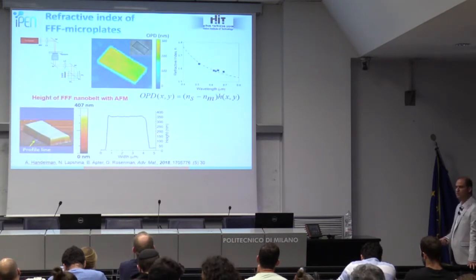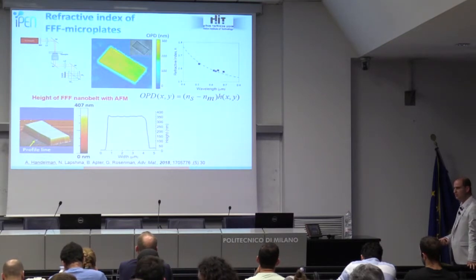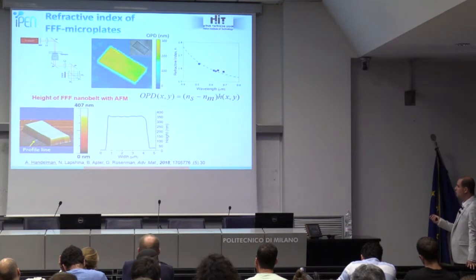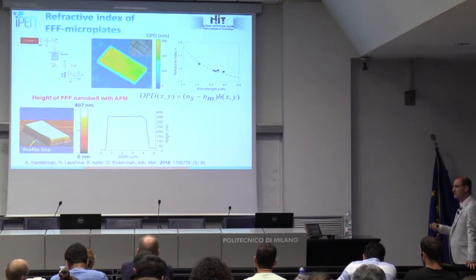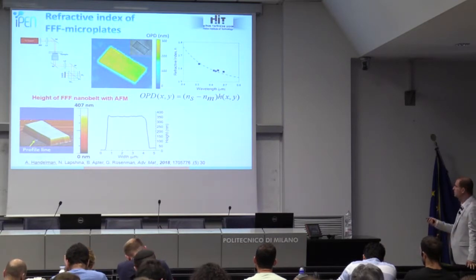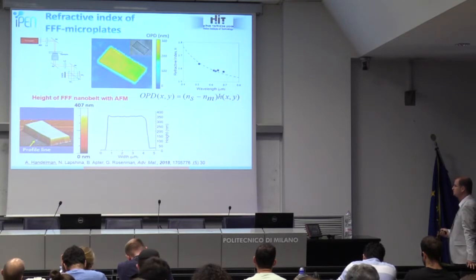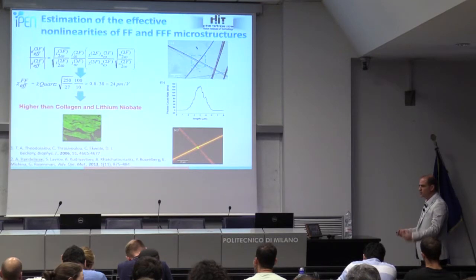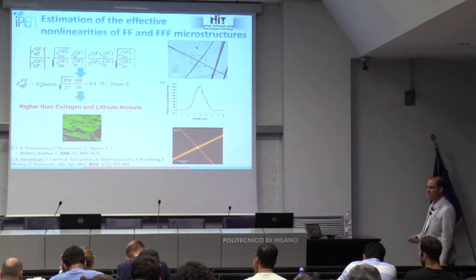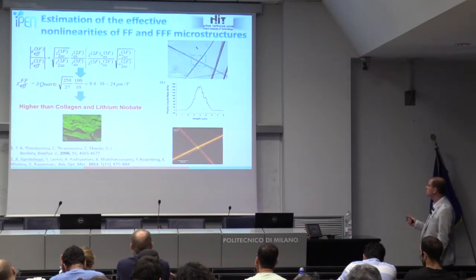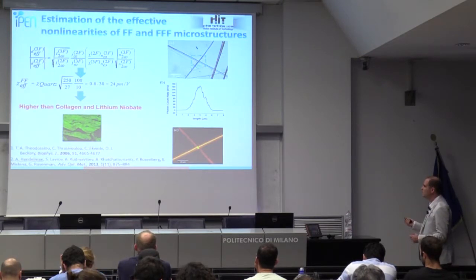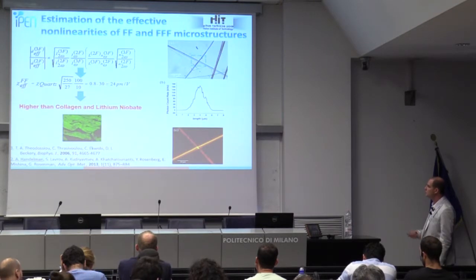The refractive index of this kind of peptides can also be estimated from another microscopy technique, which is interferometric phase microscopy. So if we know the thickness from, for example, AFM, and we get the OPD, which is the phase delay of our peptides, we can estimate the refractive index. I do it very fast, actually. We did it to find the effective chi, to understand the effective nonlinearity of our peptides. For example, in FF, we get 24 picometer per volt, which is much higher even than collagen, close to or higher than lithium niobate, which means that it is a very good material.